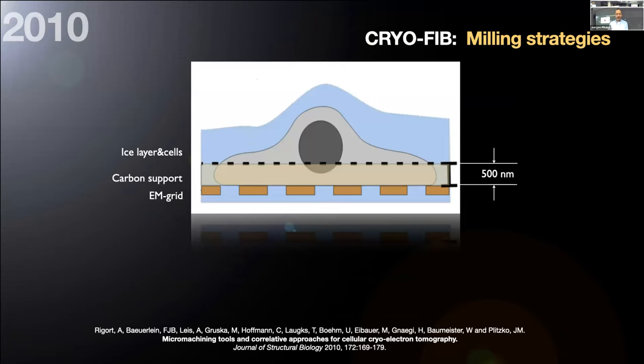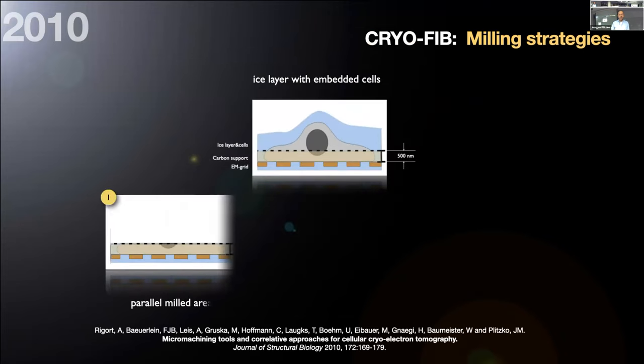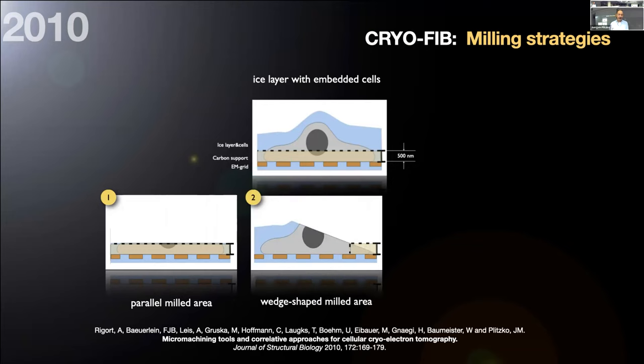The one strategy is, of course, to mill the whole grid. But that will take a long, long time with the gallium beam because the ablation rates are very, very slow. So you would need weeks until you have a whole 3 millimeter diameter grid milled. Then there was that pilot study by Mike Marko, where he did a wedge. At the leading edge of the wedge, you are thin enough, but you're not homogeneously thin, depending on the angle of the milling.